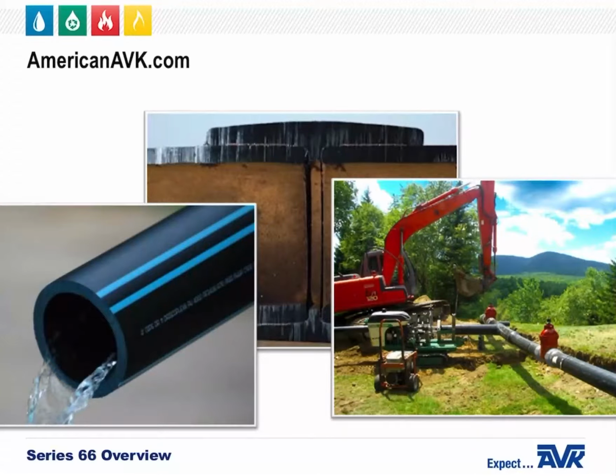PE pipe ends can be fused together to form a self-restrained, leak-free pipe system. The fused joints are in fact stronger than the pipe surrounding the joint, and PE pipe systems will last over 100 years with no pitting, cracking, corroding, or any other typical failure problems of iron pipe systems. In fact, PE has the lowest failure rate in the market.